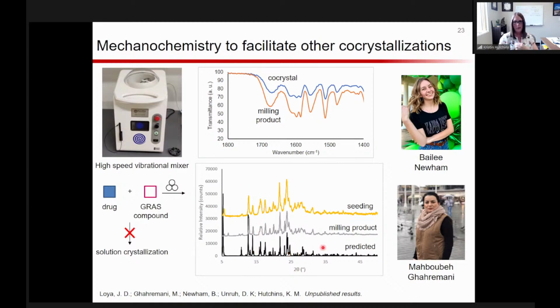And then you can see here on the bottom, just one example of our predicted powder pattern. Our product from milling shows really good correlation. And we can also take that crystalline powder from milling. We can go back to solution, drop that powder in.